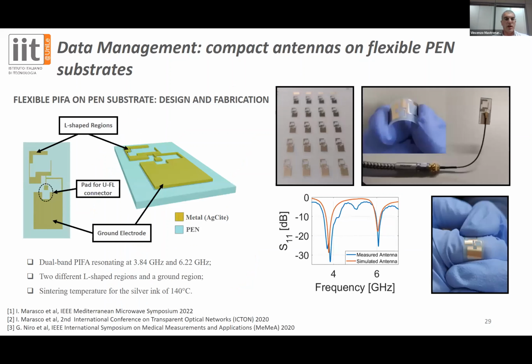The PIFA antenna is composed of the dielectric and the conductive ink directly printed on the PEN substrate. It consists of two L-shaped regions and a ground electrode, and we also included in the antenna a central pad that is designed to directly weld a U.FL standard connector. Then we tested this antenna to see the resonating behavior, showing that the antenna is able to resonate in a dual band with two resonant peaks at 3.8 and 6.2 gigahertz.